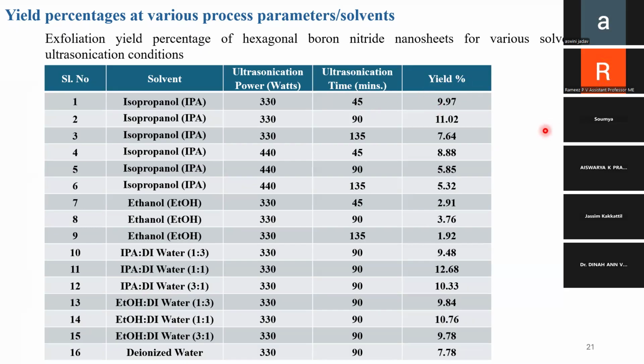Then I thought of changing the time. In another experimental trial, I changed the time to 90 minutes. I got 11 percent. I changed the time to 135, and I got 7.64. Then I thought of changing the power, and with different timings, I got these yield percentages. Then I took another solvent, ethanol, with 330 ultrasonication power.